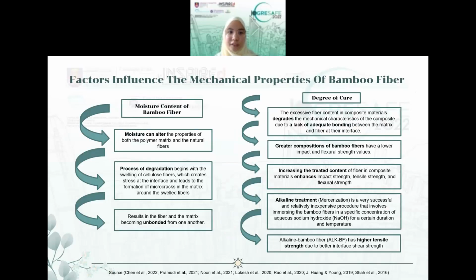So now we go through the moisture content of the bamboo fiber. We know that moisture content can alter the property of the polymer matrix and the natural fiber itself. The process of degradation will cause swelling of the cellulose fiber, which creates stress at the interface and leads to the formation of micro cracking in the matrix around the swollen fiber, which will cause unbonding between the fiber and the matrix.